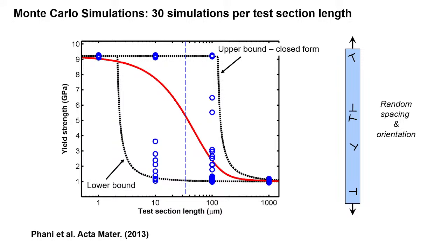And so if you now do this Monte Carlo simulation for these different cases, and these are again Phani's results. So when the size of the specimen is small, if you do 30 simulations, they all land right on top of each other. If you're way over here, very large specimens, they all line up on top of each other. And then somewhere in between, you'll get this distribution, right? But what is interesting about this distribution is not that once you cross into this boundary, these distributions are uniformly distributed. Actually, the closer you are to the upper bound, the more the data points are clustered over here, and the closer you are to this lower bound, the more the data points are clustered around there.